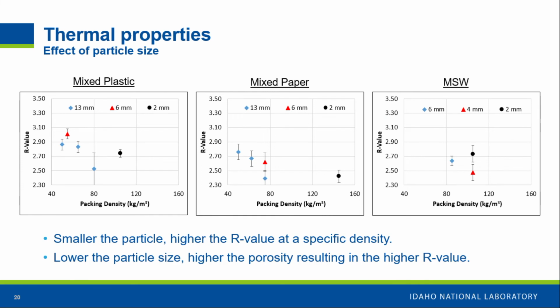This figure is telling about the effect of the particle size. You can see that for a specific packing density, if we reduce the particle size, we saw an increase of the R value. This is because when we make smaller particles, as we saw in the porosity, we get a more porous structure when we reduce the size. When we have a more porous structure, we have more air trapped in it. That means we are reducing the heat transfer. So we got a higher R value, meaning less conductivity.